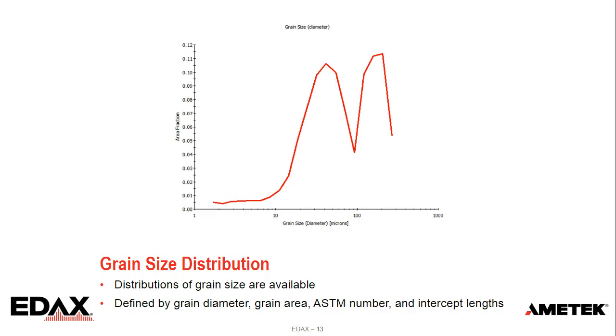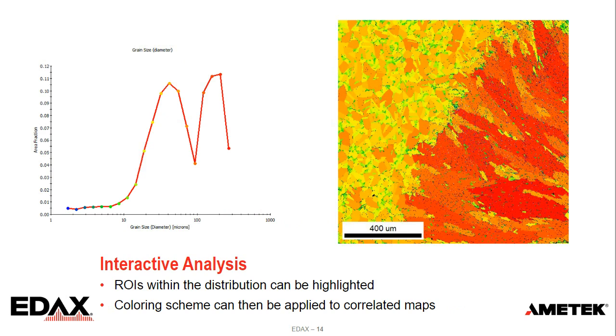And of course, if we know what the grains are in terms of pixels, we can figure out a grain size distribution. That's shown here. We can define this grain size distribution a number of ways. I think the default often that people think about is in terms of diameter. That's an easy one to get out. That's the default, to show diameter. But of course, as we look at some of these grains and grain shapes, diameter doesn't always make sense when they're non-equiaxed grains. So we can do grain area, we can do ASTM numbers, we can do intercept length. There's a number of different ways of representing grain size that can be applied to the particular microstructure. And then we can do some fun things to try to link these things.